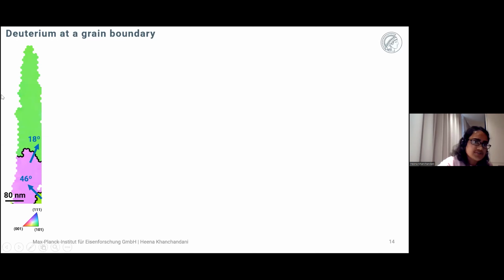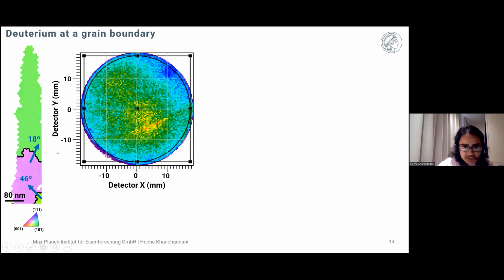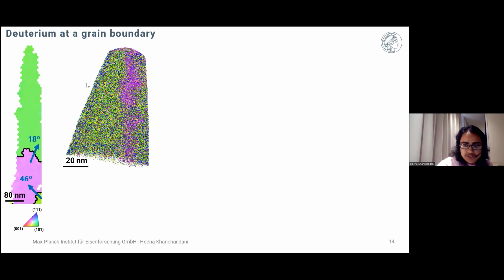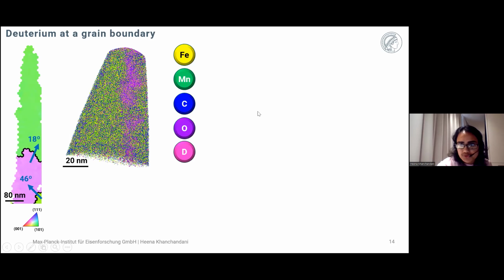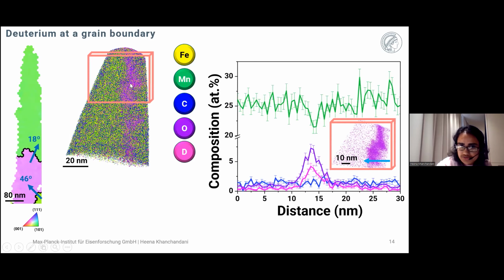So this protocol was followed, for instance, on this sample, in which we confirmed by transmission Kikuchi diffraction that there are 2 grain boundaries in this sample with these misorientation angles. And we first did the pre-analysis, and in this pre-analysis, when we saw that the grain boundary had evolved, we stopped the analysis and transferred the sample to the reactor hub module for charging. And after deuterium charging, we observed the segregation of both deuterium and oxygen at these grain boundaries.